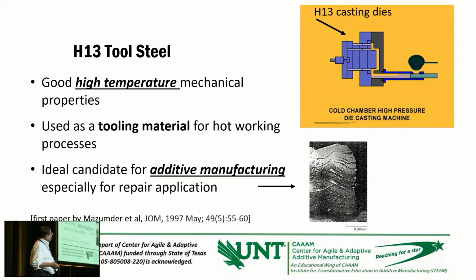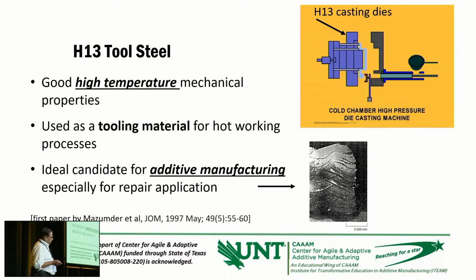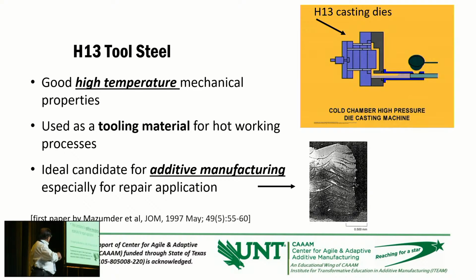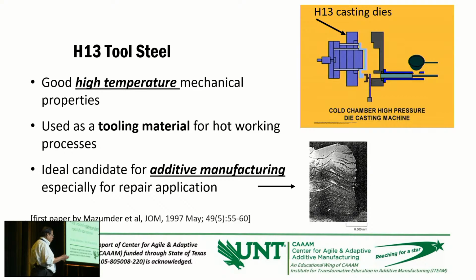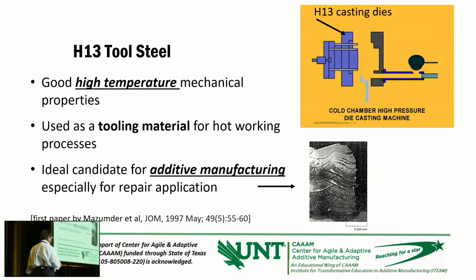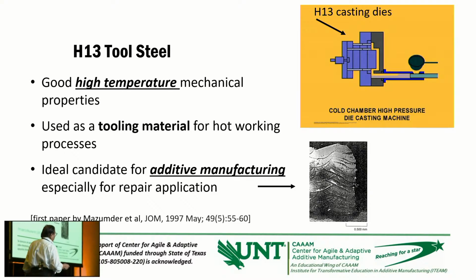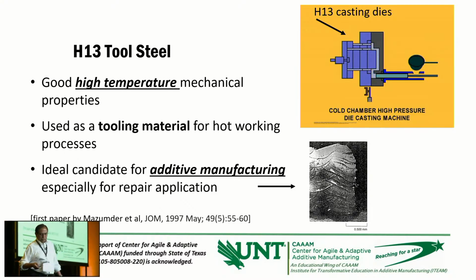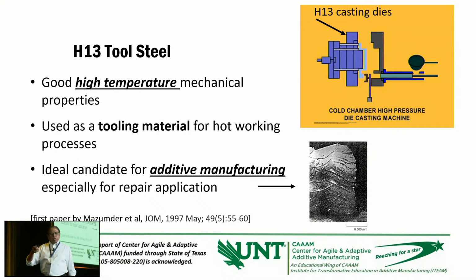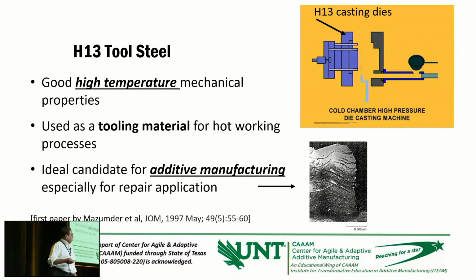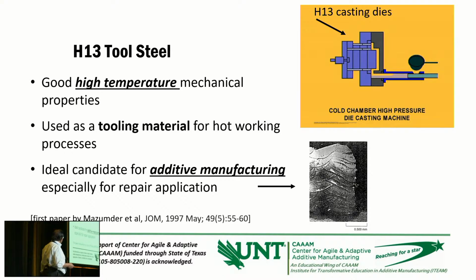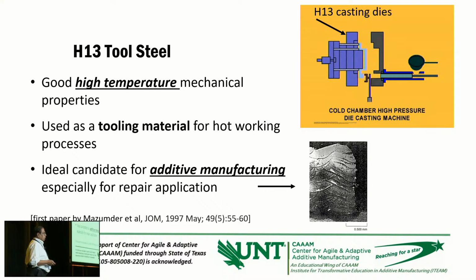So all these components are produced thousands in a day. The way they process this material, the casting, is they pour the aluminum in the die, and then the die moves into the next station where it is cooled by the water spray to reduce the time of the cycle, and then that die is again used for the next casting. So it is continuously heated and cooled down in the process, so it has to resist the thermal cycle. So this is a very tolerant material for that purpose.